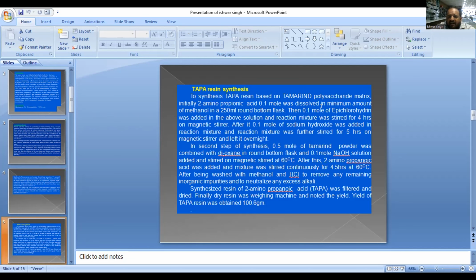And then I took 0.1 mole of epichlorohydrin for the chlorination. So I did the chlorination with the help of epichlorohydrin, in the same stoichiometry, that is 0.1 and 0.1 mole. After this, 0.1 mole of NaOH, sodium hydroxide, was added in the same stoichiometry, and I stirred the process for chlorination for about 5 hours on a magnetic stirrer, and left it overnight.